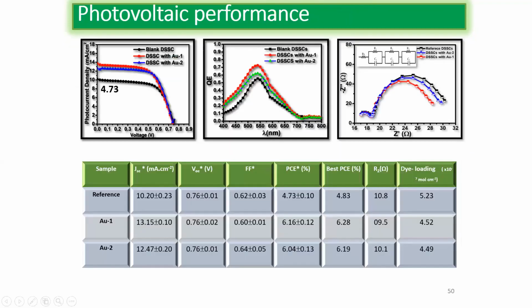And the absorption enhancement is really very drastic, approximately 4.73 to 6.04%. This is approximately 30 to 35% of the enhancement. And this is IPCE. We see that at longer wavelengths, where the particular dye is not absorbing, this gold nanoparticle is able to absorb light even better.